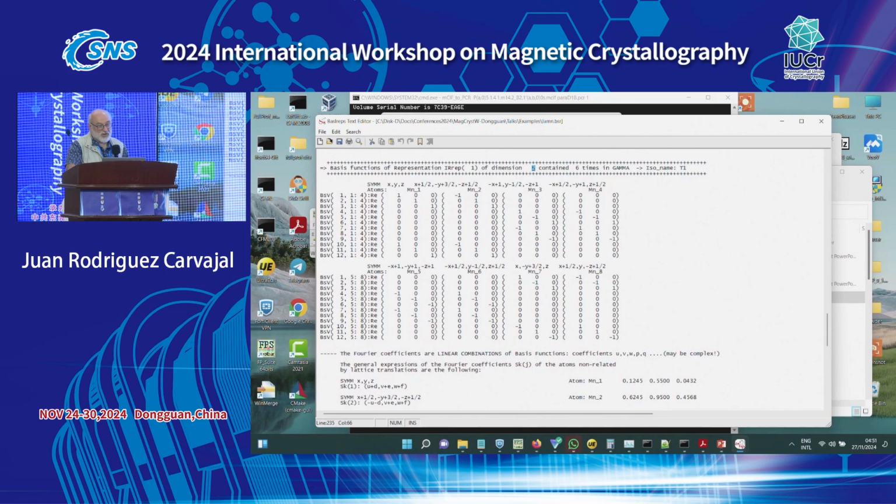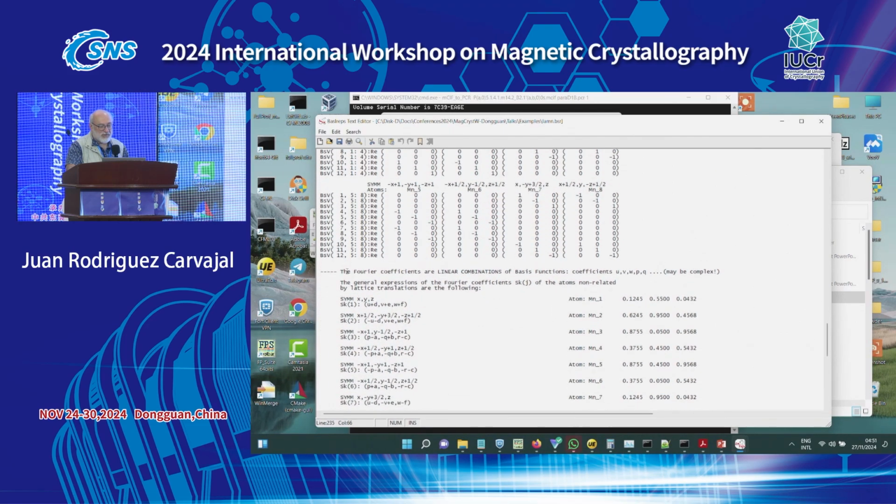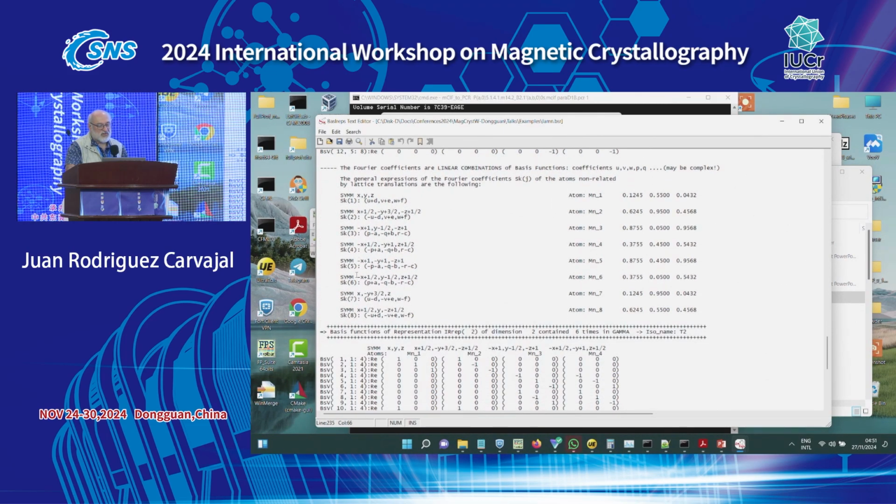This is impossible. Normally you need only, in that case, only 3 numbers. But you see here, how are the coefficients? Very complicated thing. And this is the advantage of using isotropy group, a classification of how you get these basis vectors. Then you have a lot of coefficients here, and then you cannot work with that in general. You could do the work before we had all the development of the isotropy. I was doing that by hand. I was looking for different symmetries, just looking at these coefficients here.